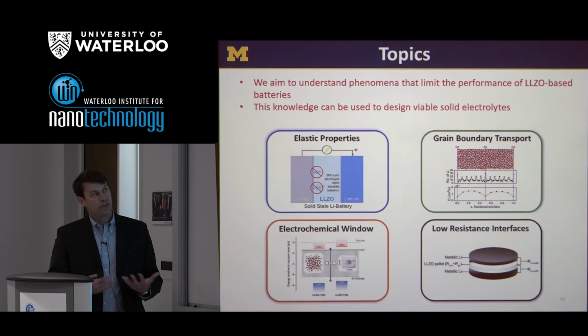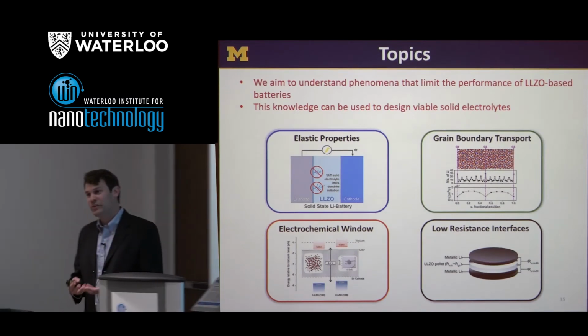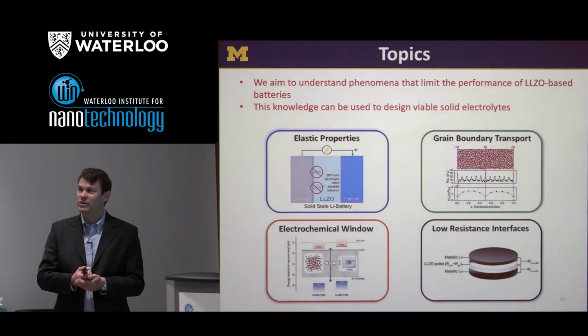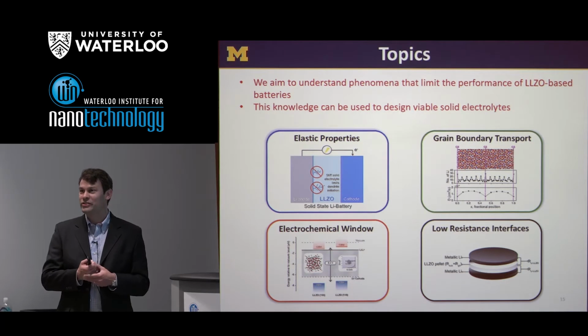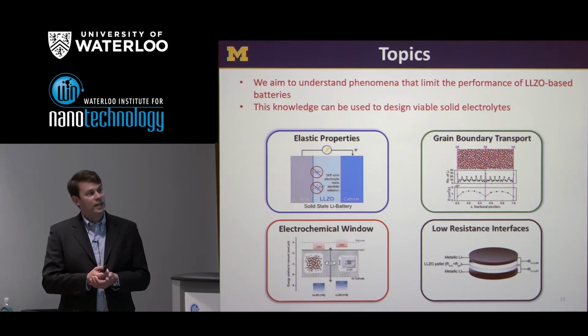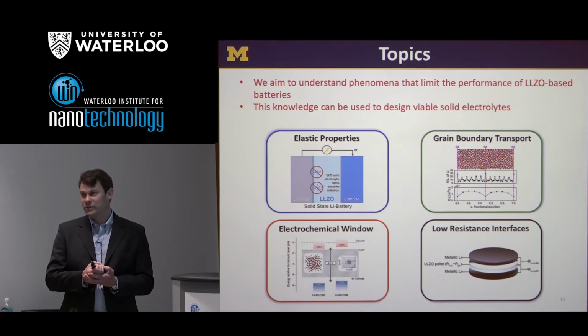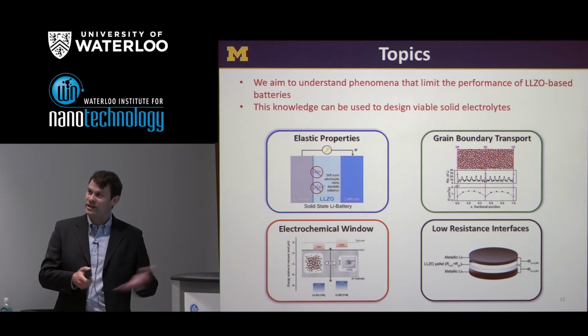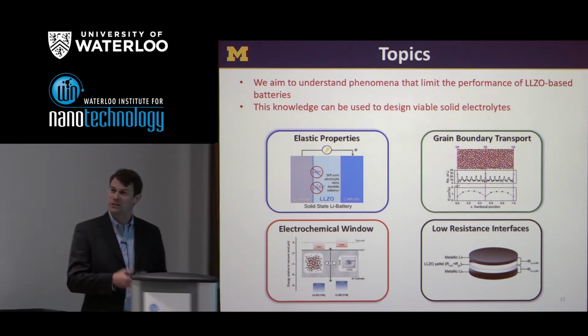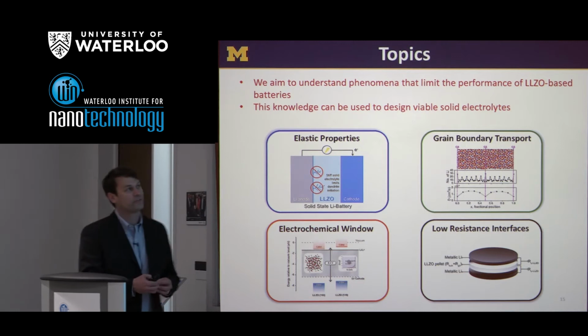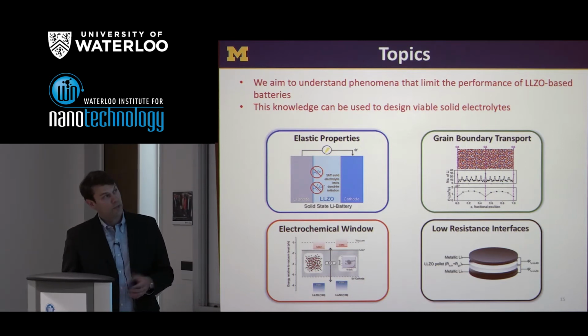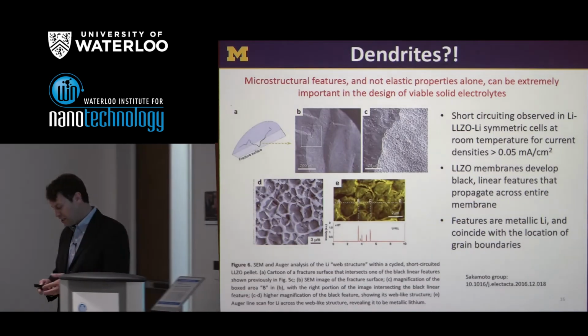So mechanical properties look good for LLZO, and you might have said, well, that probably is unexpected. Most oxides have a high shear modulus anyhow, or are relatively stiff. It turns out there are other solid electrolytes, for example, LGPS, that don't satisfy the Monroe-Newman criterion. They're actually good ionic conductors that are relatively soft. So one needs to be careful. And we've also seen some surprises, even with satisfying the Monroe-Newman criterion.